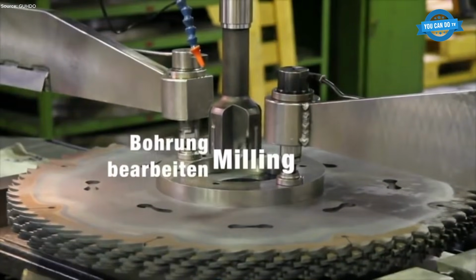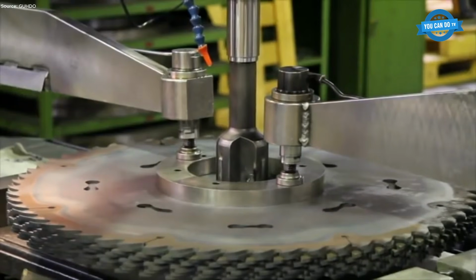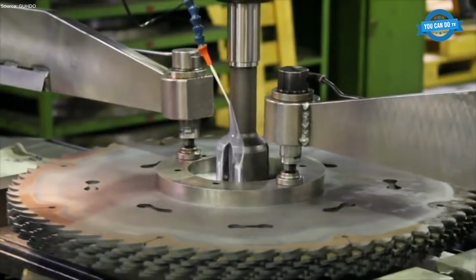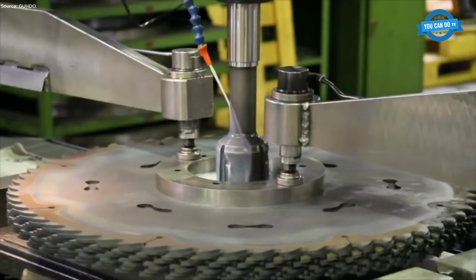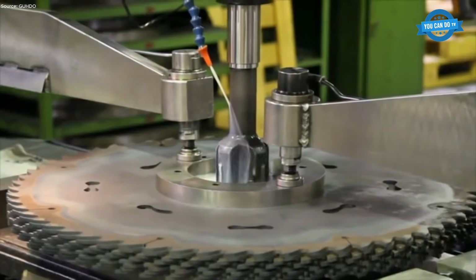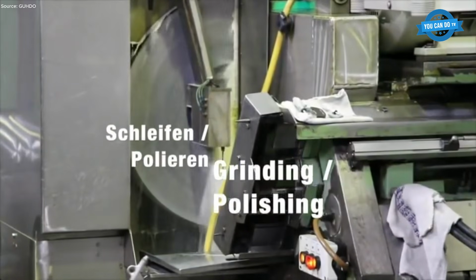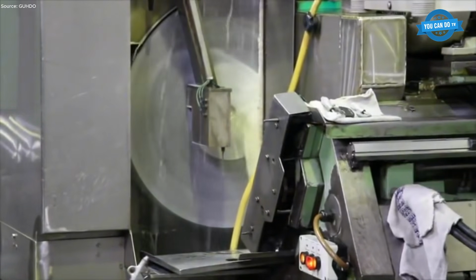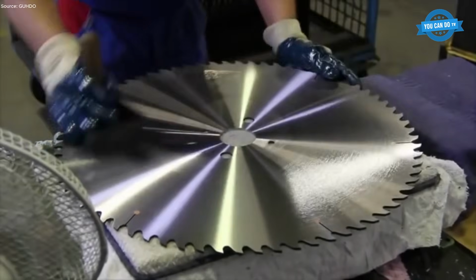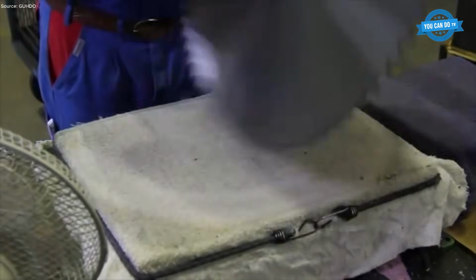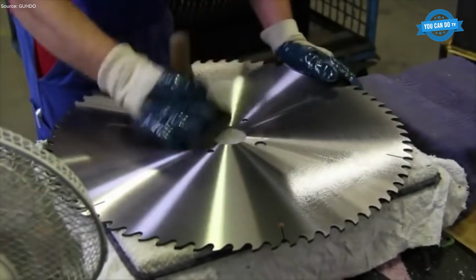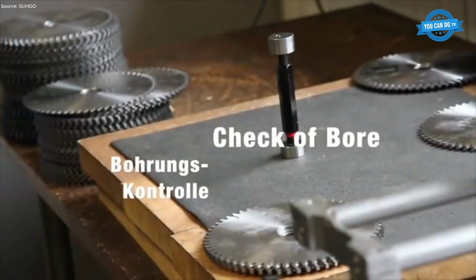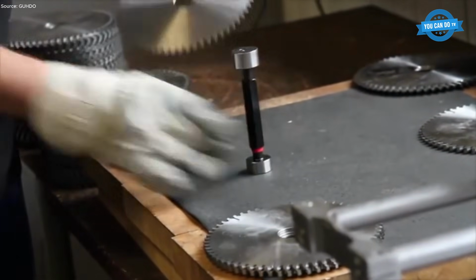Once heat treated, milling operations refine critical areas such as slots, expansion grooves, and reference surfaces. These features help control vibration, thermal expansion, and noise during operation. After milling, the blades are lightly oiled to protect against corrosion during subsequent handling. To prevent magnetic interference during cutting, each blade is demagnetized. The bore is then inspected with precision measuring equipment to ensure perfect concentricity and fit on the arbor. Any deviation at this stage could cause imbalance at high rotational speeds.